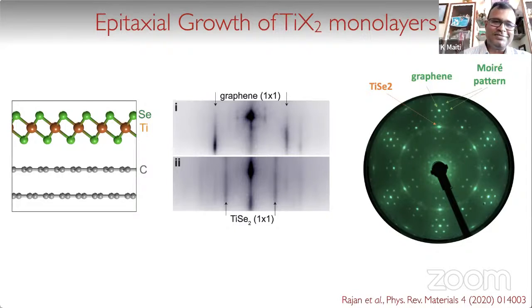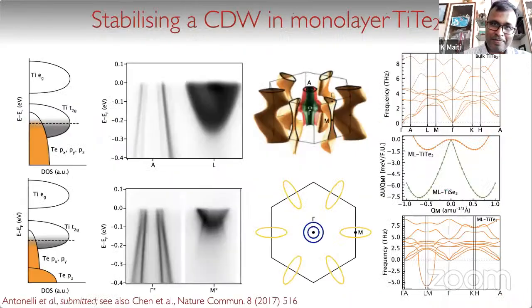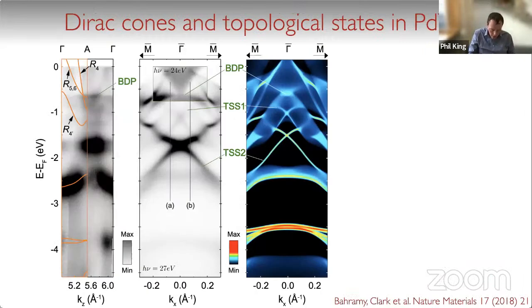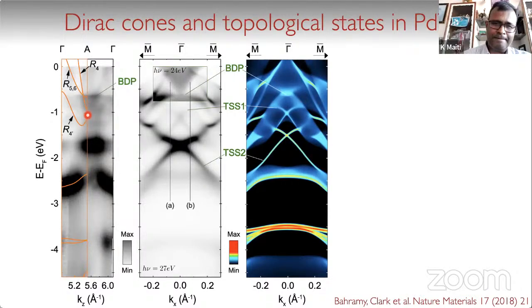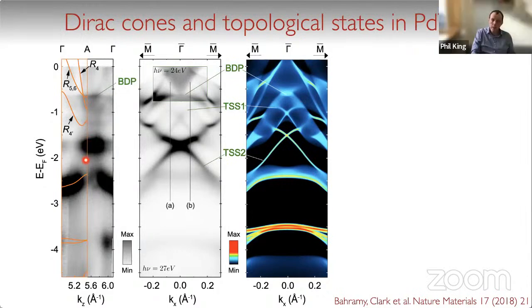The first system that you have shown, you have shown these two topological surface states, TSS1 and TSS2. So this TSS1 was pretty weak in intensity. Is it because of the twinning that you see these two states, or are they coming from the same surface? No, they're coming from the same surface, but they're coming from separate band inversions. So there's one inverted gap here, which gives TSS1, and one inverted gap here, which gives TSS2. This inverted gap you see is a complete kz-projected gap.